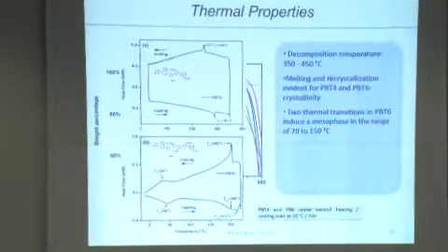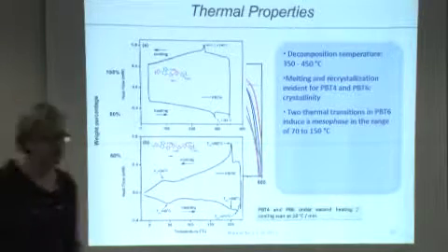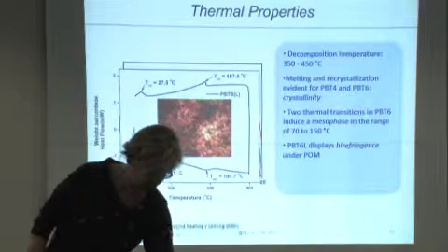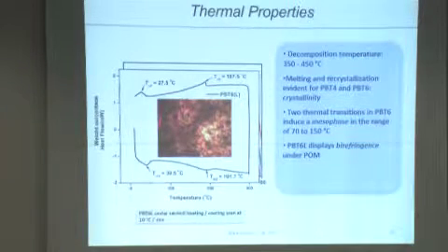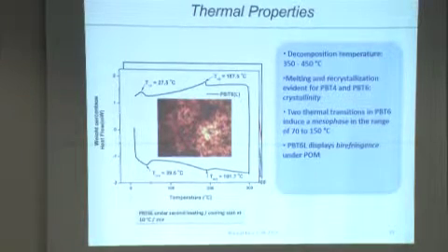Thermally, we see a melting peak for one of the materials. This is the higher molecular weight material. For the lower molecular weight material, we actually see two transitions in the thermal analysis. And it's possible that we have a mesophase here, which, again, with the Srinivasaru group, we were able to do some polarized optical microscopy showing that there is birefringence, which may be reminiscent of liquid crystallinity.